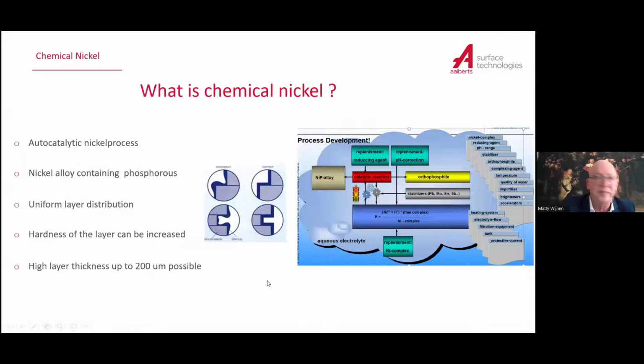Then chemical nickel. Chemical nickel is a coating which is totally different. Chemical nickel is a chemical coating, and it's called an autocatalytic nickel process. On the right side, you see a small sketch of what's happening in a chemical nickel process. It's a very complicated process. In principle, you have a solution in which nickel ions are dissolved. You put a reduction agent in that bath. Normally it's sodium hypophosphite, which is used for that.